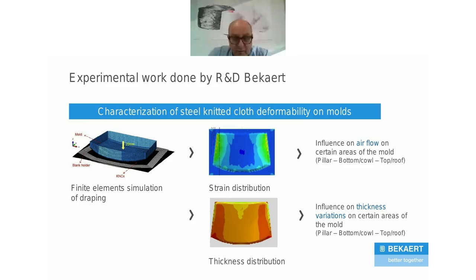If we look at the strain distribution, we see more or less the same, that you have a different kind of thickness at the sides, so on the pillar sides, on the cowl, and also on the top. So we have to keep that in mind when you start to press glass, that this can also create some local thickness variations in your glass. The outcome of that was quite interesting, to see that the kind of pre-straining was necessary.